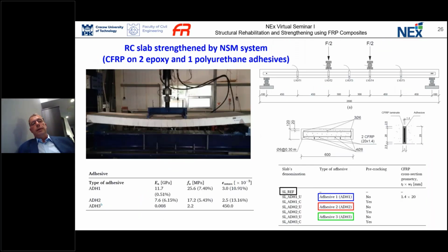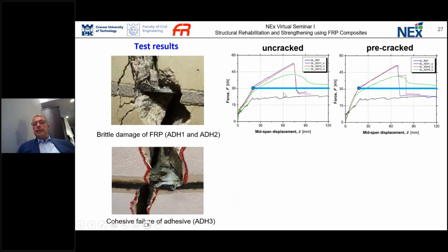It was also confirmed in another kind of test in Portugal. We had a slab, but we applied not an externally bonded system, it was a near surface mounted system, so carbon fiber was installed in a groove at the bottom of the slab with 2 kinds of epoxy adhesive. You can see 11,000 megapascal stiffness. Another one was 7,000 megapascal stiffness, but the polyurethane flexible bonding was only an 8 megapascal system. So we tested 2 kinds of structures. One was uncracked and another was pre-cracked when we installed the NSM system.